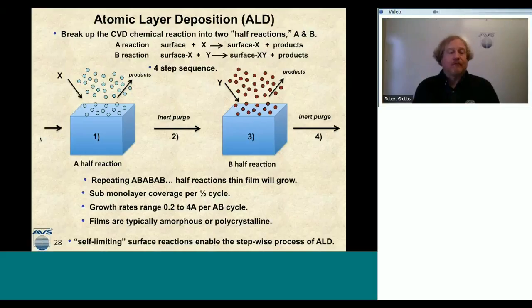grow. Now what's important is that each one of these half reactions really puts down less than a monolayer of coverage per half cycle. So I'm really not growing single crystal unit cell films at a time. I'm growing partial monolayers of films at a time. So that's why we'll see these growth rates. I shouldn't call it growth rate. It should be growth per cycle of about 0.2 of an angstrom to 4 angstroms of film growth per AB